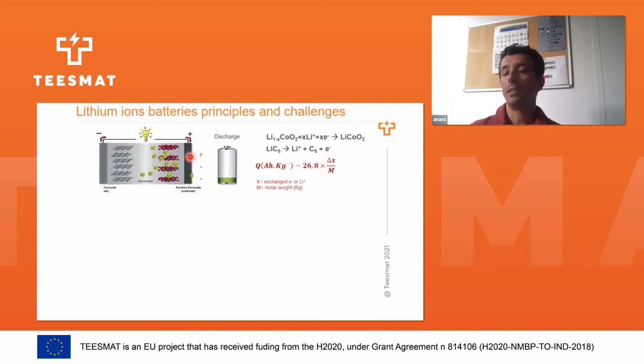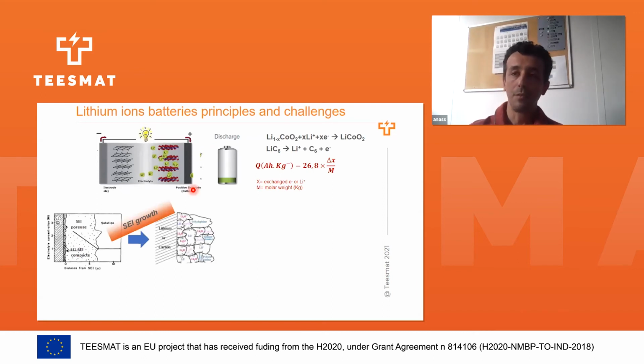to the mass of the active materials. And we have to emphasize different problems in lithium-ion batteries. First is solid electrolyte interphase growth: what is the mechanism of the growth, what is the nature of this SEI, how it is organized. This is the first model, developed by Peled, but it is still under debate nowadays, because it depends strongly on the electrolyte solution and the electrochemical conditions. There are many parameters that play on the nature and the thickness of this SEI.